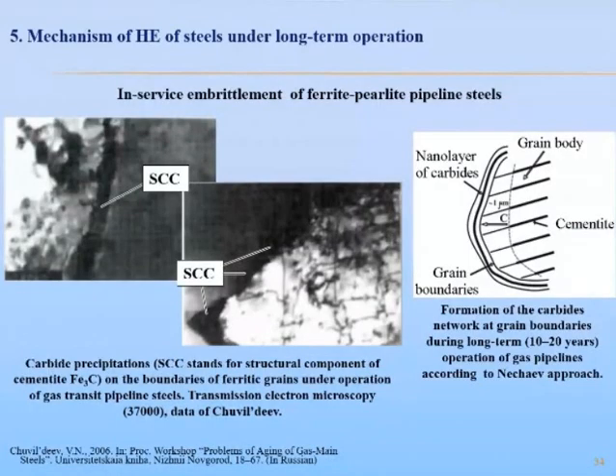So, a mechanism of hydrogen embrittlement of steels under long-term operation. The embrittlement of pipe is a well-known phenomenon, but the precise role of hydrogen in this process is not well understood. And here a new model is proposed wherein hydrogen facilitates carbon diffusion in ferrite-perlite pipeline steels under operation, which leads to carbide enrichment, both grain boundaries and intragranular defects, and thus promoting a cleavage fracture. So the background is as follows.